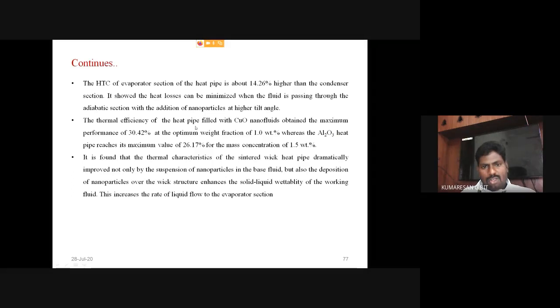Then the thermal efficiency of the heat pipe filled with copper oxide nanoparticles obtained a maximum percentage of 30.42 for the optimum weight fraction of 1%, whereas the aluminum oxide heat pipe reaches its maximum value of 26.17 for its optimum concentration of 1.5%. Then it is found that the thermal characteristics of the sintered wick heat pipe dramatically improved not only by the suspension of nanoparticles in the base fluid, but also by the deposition of nanoparticles over the wick structure, which enhances the solid-liquid wettability of the working fluid.